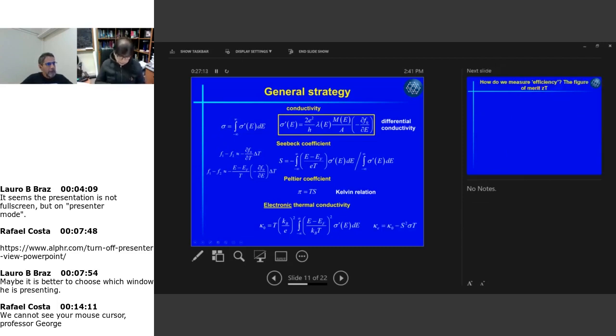kappa zero. And remember that kappa E, the one that is added to the kappa of the lattice, is kappa zero minus S squared sigma T. If I wanted, I could write an expression for kappa L, where kappa L is the lattice thermal conductivity, that is, how the lattice transports energy given a difference in temperature. And you can use the Landauer approach, and so on and so forth. Exactly the same idea: count the number of channels, et cetera, do an integral, and you get an expression that is very similar to that. In our work, we didn't calculate the kappa L for the lattice, for the phonons. We used what was available in the literature.